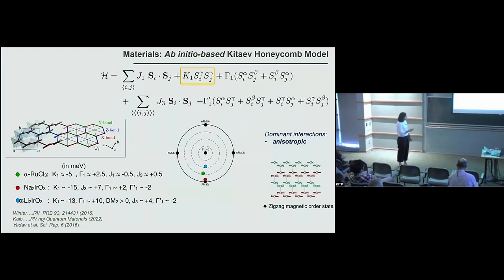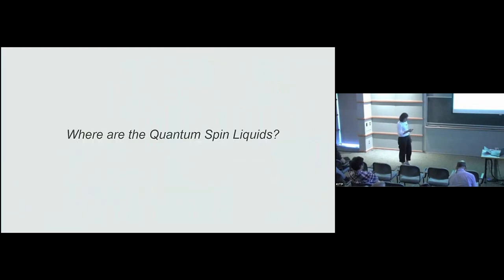And you can see that, for instance, for the iridate materials, the energy scales are larger, and the reason for that is because here one is dealing with iridium and not with ruthenium, so the spin-orbit coupling is stronger, and this is also changing the scales. So all these systems that we show here, basically alpha ruthenium trichloride and sodium iridate, order in a zigzag long-range order. Alpha lithium iridate has a spiral order, as has been seen by Radu.